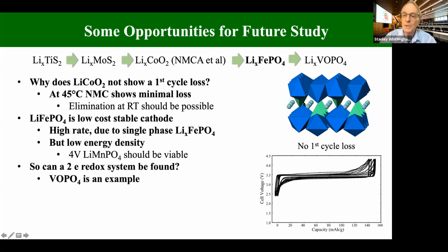And it's interesting, this material, which has this tunnel structure where the diffusion is essentially in one direction, shows no first cycle loss, as we show in the plot beneath here. These essentially lie on top of each other. So again, it's a clue we should be able to do it. What is interesting, this particular material is probably the highest powered cathode known, even though it's an electronic insulator. So it can be made to react fast, and we did this by making this into a single phase reaction. But it has too low an energy density, so we are hoping to commercialize a manganese equivalent of that, which gets it up to 4 volts.